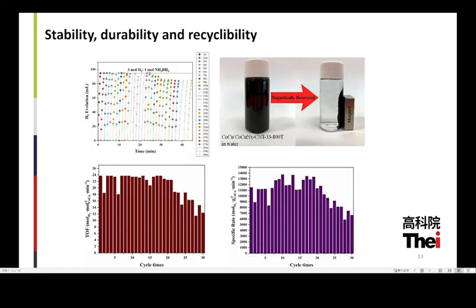To test the cobalt-copper stability, durability, and recyclability, we ran the experiment 30 times by adding ammonia borane continuously without filtering the catalyst. The catalyst can be effectively separated from the solution by simple magnetic manipulation, like the top right photo. The 30-cycle result shows a decay after the 18th cycle, but it is a good result so far, and it shows it is recoverable with high stability and durability.